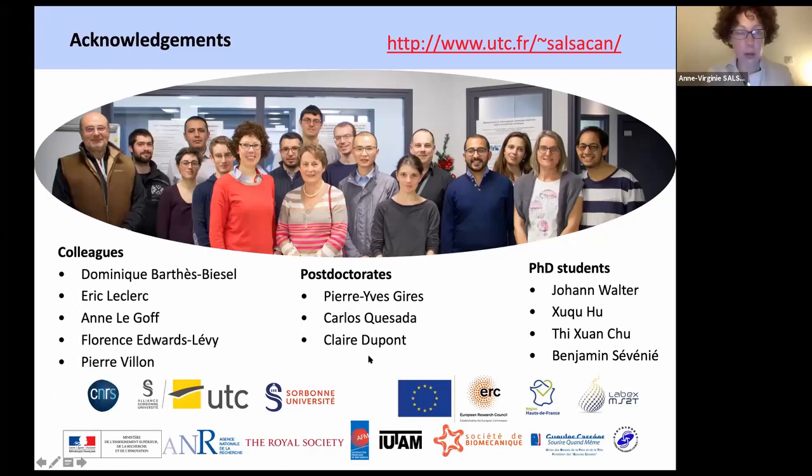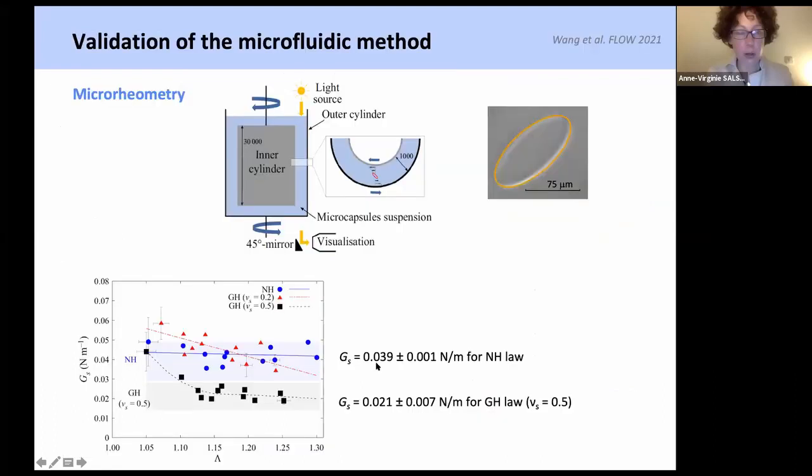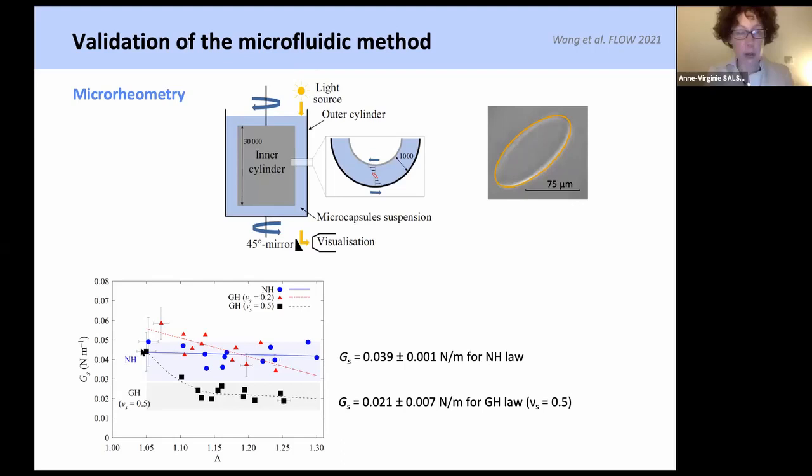That was the mean and max values, but the mean is the value indicated here on the right. And you see that it fits quite well for measurements that are so complex. We end up having a very good precision. And then the constitutive law: you know that you have the right constitutive law if the value you find is independent of the deformation. In that case, you find the right behavior. You're well modeling your capsule. So that's the criterion, to have something as constant as possible.